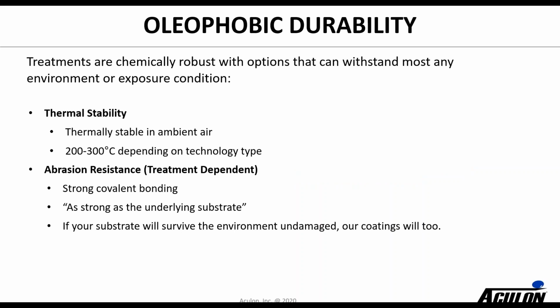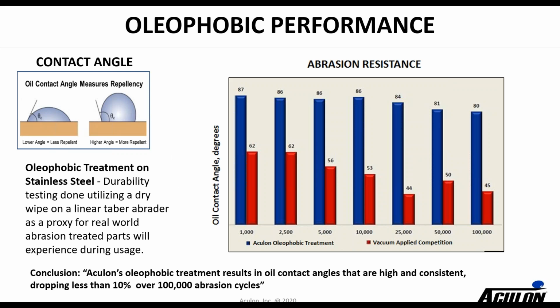Oleophobicity durability is important, and these treatments are chemically robust, and they can withstand a lot of environmental exposure. So, for example, for thermal stability, they're thermally stable in ambient air up to 200 to 300 degrees C. They are abrasion resistant. We have treatments that give strong covalent bonding, which is as good as the underlying substrate. And if you don't damage that underlying substrate, then our coating will survive as well. And here's an example of that. This is some testing showing abrasion resistance on stainless steel.